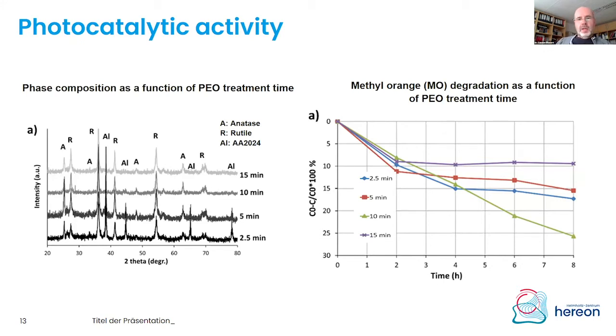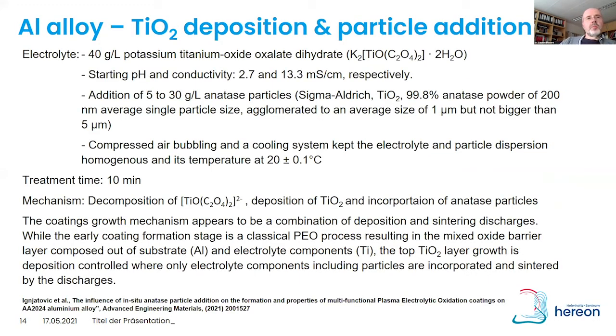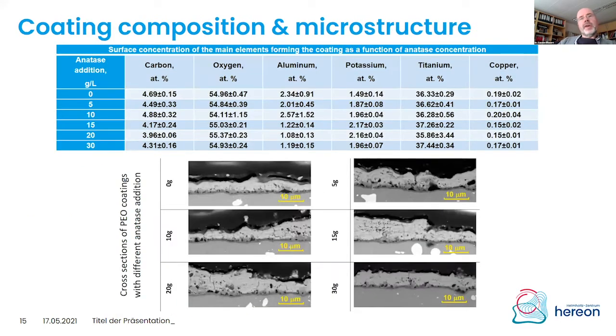And this information we took and wanted to optimize. This second part of the aluminium presentation deals with how we can now get a better ratio between the anatase and the rutile. For that, we have again added, similar to the magnesium example, anatase particles to the electrolyte, from 5 up to 30 grams per liter. 30 grams was somehow the upper limit. More we could not add, because then we had problems with the stability of the discharges in the electrolyte. So again, the same mechanism, but now with added particles.